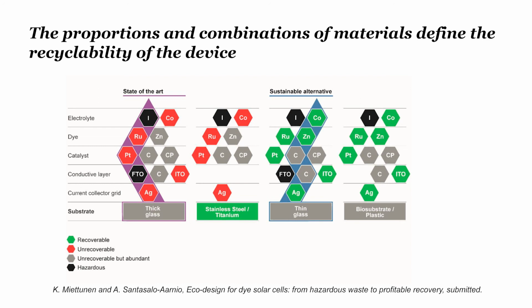So when we look at what is the conventional state-of-the-art of emerging solar cells, we can see that all the materials fall into the categories that it would be impossible to recover them, and we also lose expensive and rare materials, as well as are faced with materials that form toxic gases in the processing. But even with a simple change in the system, for instance, changing from a very thick glass that is conventionally used to, for instance, thin flexible glass, and choosing different materials options for different components, we arrive to the situation where all expensive materials could be retrieved and only abundant materials would be lost.